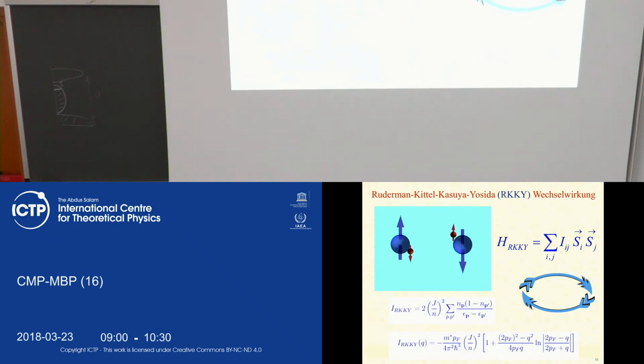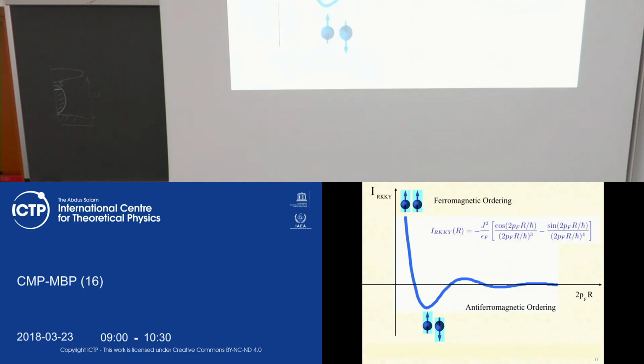interaction. Sorry, it's written in German because, never mind. To make this story simple, with Anton Parafilo you discussed the Lindhard function, which is a polarization operator, a polarization loop. This is the Lindhard function, you can really recognize it. So this is the same polarization loop which you computed with Anton. Now, if one takes a Fourier transform of this Lindhard function, what one finds is that the Fourier transform is an oscillating function of the product of Fermi momentum times the distance. So this is the same Lindhard function after taking the Fourier transform as a function of the dimensionless parameter 2 p_F r.